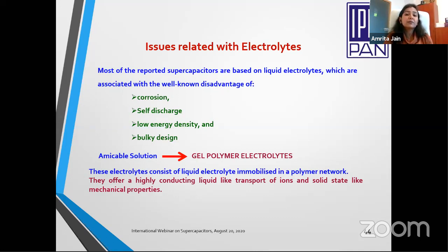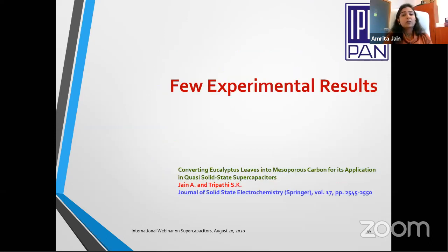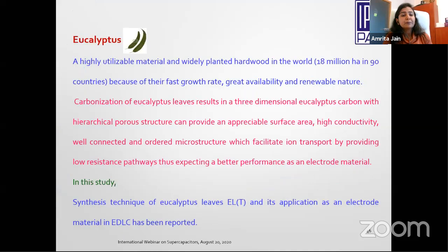In case of liquid electrolyte, you can achieve a maximum of up to 1 volt or something. But in case of gel polymer electrolyte with certain chemicals, we have also achieved up to 4 volts, which is very high, really very high. Now, a few of my experimental results are already published in the Journal of Solid State Electrochemistry.